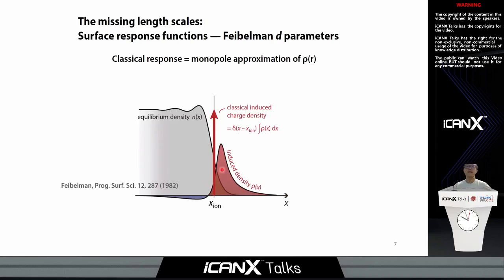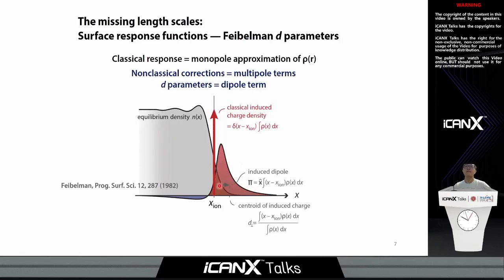So the exact deviation of the induced polarization away from the ionic interface is defined as the Feibelman d parameter, the perpendicular term. And analogously, you can define something similar for the parallel term of the d parameter, which is the centroid of the derivative of the surface current. If you think about this electromagnetic response, we can understand the classical response as a monopole approximation of the induced polarization, while we can treat these d parameter terms as the dipolar excitations.